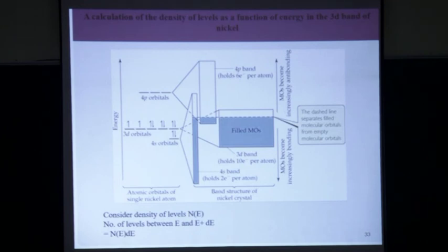If that exchange integral is positive, then the energy is lowered by the spins being in the same direction, which means you have ferromagnetism. If the exchange integral is negative, then it favors the anti-parallel state, which is antiferromagnetic.